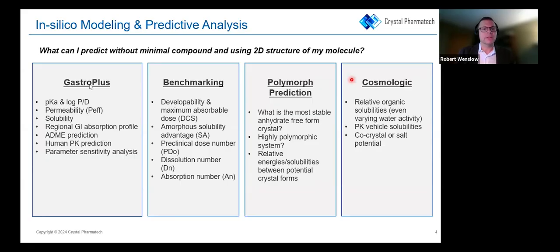We also use a software called Cosmologic. Again, these aren't the only tools out there. This is just some examples that we work with specifically to get relative solubility. It works best when you have at least one accurate solubility value, but then you can go in and predict solubility in binary, ternary solvent systems, changing water activity. We also use Cosmologic a lot for co-crystal formation and trying to find the best synthons, the best co-formers to use in a screening. And it's actually not bad. It does a pretty decent job of rank ordering some of the co-crystal formers, and at least telling you if it makes sense to do a co-crystal screening.